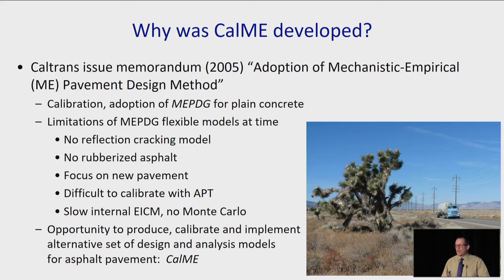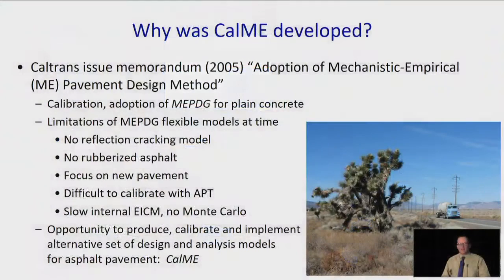98% of the money that we spend is on overlaying cracked and jointed concrete and cracked asphalt. Our main distress mechanism in the state is fatigue cracks. So we needed a reflection cracking model. About 70%, 80% of the surfaces in California are rubberized hot mix, and we needed to have a method that would deal with our rubberized hot mix.